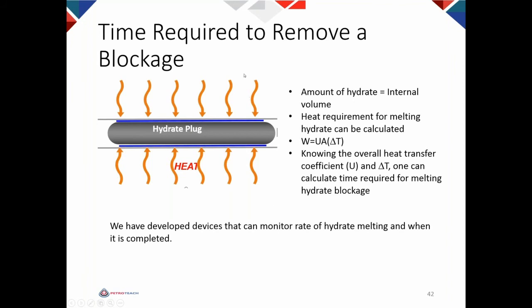So we need to provide this heat to remove the hydrate blockage completely, or remove 20%, or 10%, or 50%. People have different criteria. Some people say that if you remove 20%, for example, we can have inhibitor circulation, we can have pressure maintenance, then we can have flow, things like that. But here I'm assuming we want to remove all of it. So if we know the overall heat transfer coefficient U and delta T, we can calculate the time required for hydrate blockage removal.